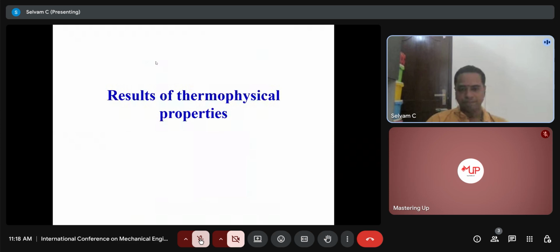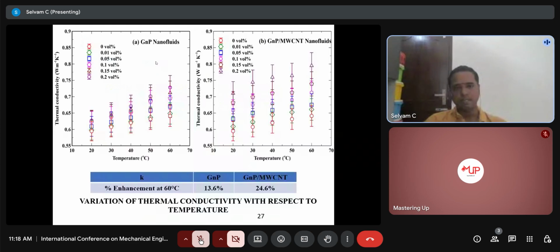And these are the results of the thermophysical properties. If you see the thermal conductivity as per the standard, with respect to temperature, it is increasing. With respect to concentration, it is also increasing. As compared to the graphene nanofluid, the graphene multi-wall hybrid nanofluid shows higher thermal conductivity. It shows 24.6% enhancement in thermal conductivity at 60 degrees Celsius.